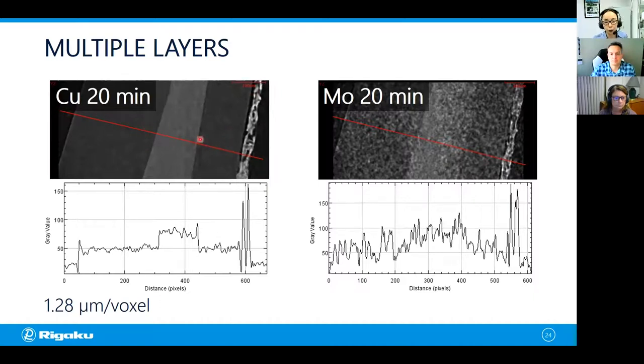And if you look at this profile, you can see the change in gray level. Those two are two different levels. With the molybdenum, when you look at the image, you can kind of tell that the center part is lighter colored, but when you look at the profile, it's really hard to tell the difference or identify the borderline.